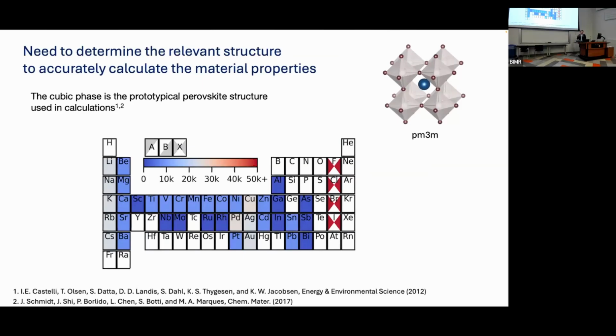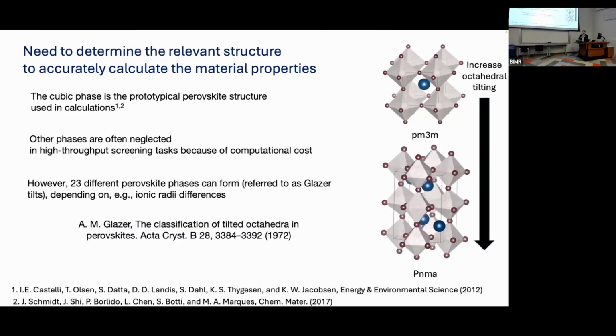But it also, by definition, limits you to just one lattice, because you've emphasized breadth in composition over actual structural diversity. That may not always be a realistic approximation, because in materials, of course, as you combine different elements, the structure can relax from something like this ideal cubic to something like this orthorhombic. And in fact, for the perovskite specifically, this has been worked out already by Glazer several years ago. There are about 23 different phases related by these octahedra tilting. Here you can see the octahedra all align, but they can adopt different tilting angles, and that structure then becomes a little bit lower symmetry. So this is a huge phase space, but most effort has been focused just on the cubic phase itself.